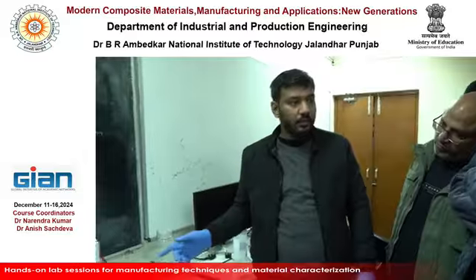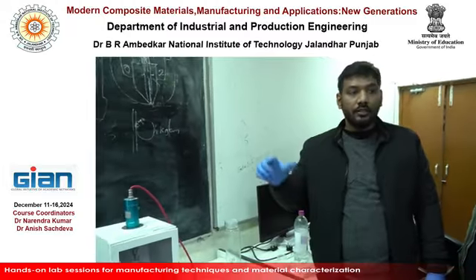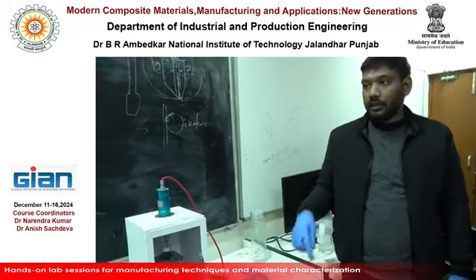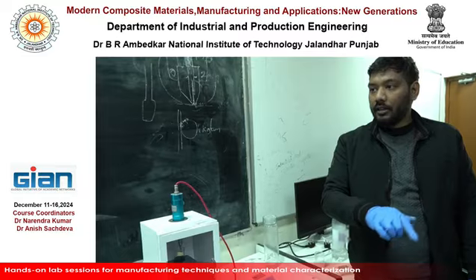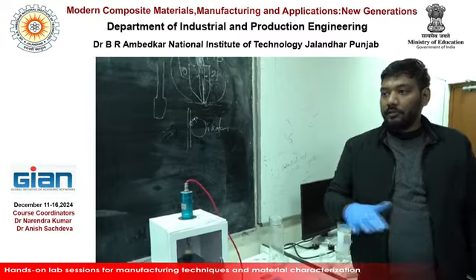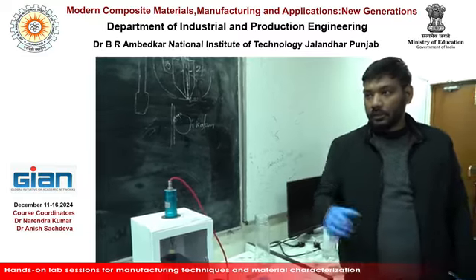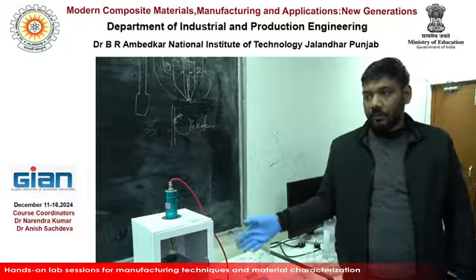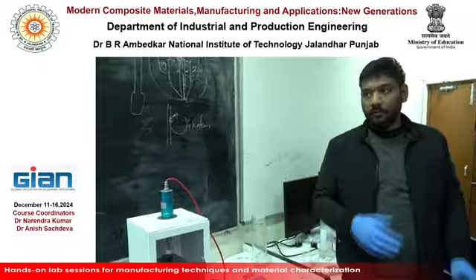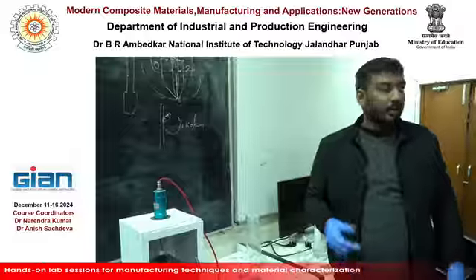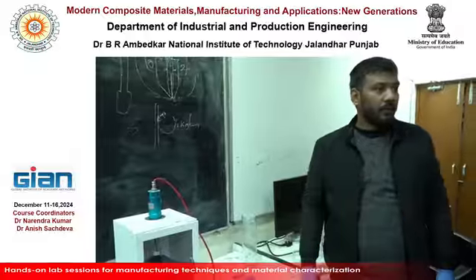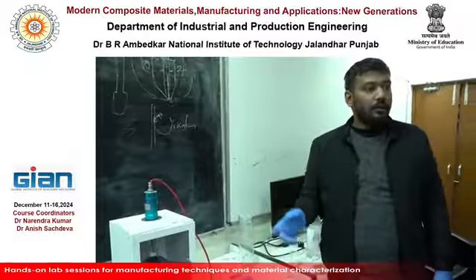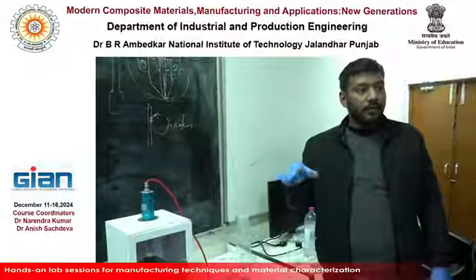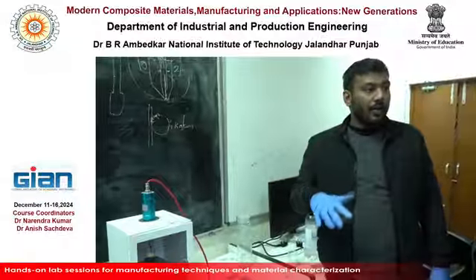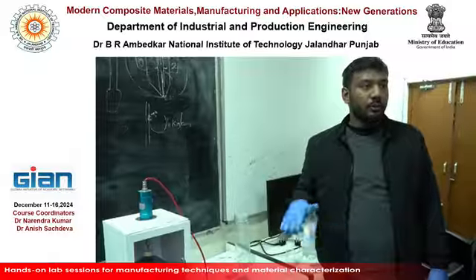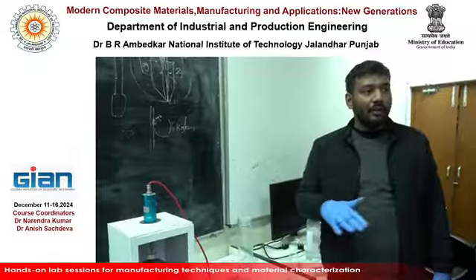With that mixing only, we mixed resin with glass microspheres and put it in a DLP 3D printer machine, and we printed dog bones. Yesterday I showed that sample. We prepared it with that probe sonicator and printed it with DLP. That is a composite material. Application-wise, we printed low dielectric constant material to use in electronic applications.